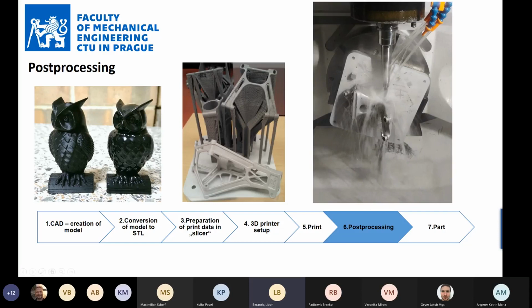Usually design for 3D printing, design for additive, means very complicated geometry, and we use the full features so that you can really have complex shapes. But if you think about the post-processing, then with the complex shape you are facing the situation that you have to be able to clamp or hold this complex shape somehow. So this again targets some kind of special fixtures, or using some low temperature melting metals like Wood's metal or bismuth, or you have to use the pallet directly. Usually when you are designing parts for machining, you are also thinking about the fixtures and the clamping. When you are designing parts for additive and the last step has to be machining, you can cause a lot of problems during the design phase if you don't think about it.